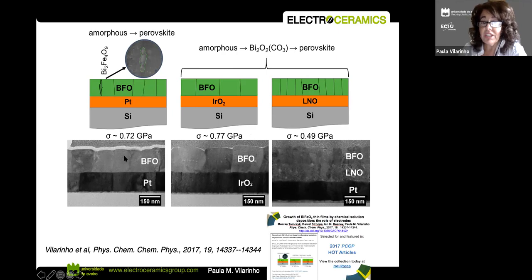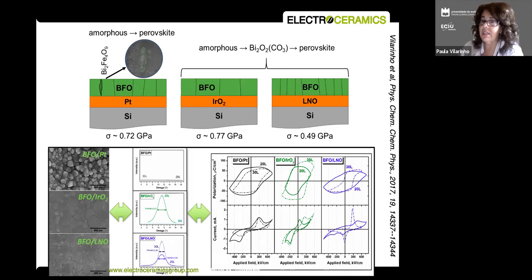And the other interesting thing is that if the stress is really high, sometimes the material doesn't like it. In some situations, the stress is so high that the material creates secondary phases. And that's something we were not expecting. By the way, to see this, we have to use high resolution transmission electron microscopy. So once again, my point here is that we can really engineer the properties. You see here, the microstructure is very different and the dielectric response is very different.